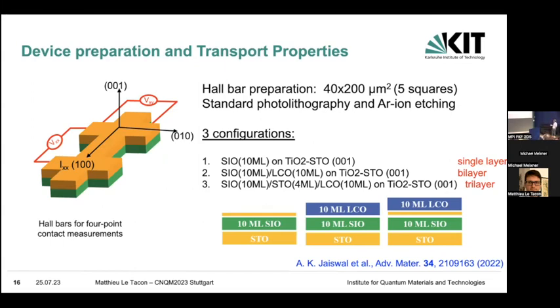And we did 3 types of systems. The first one, we just have 10 monolayers of strontium iridate on STO with a capping layer to protect it. The second one, we put strontium iridate and lanthanum cobaltate directly in contact. And in the third one, we put between the cobaltate and the iridate a strontium titanate layer to separate them and avoid direct contact.